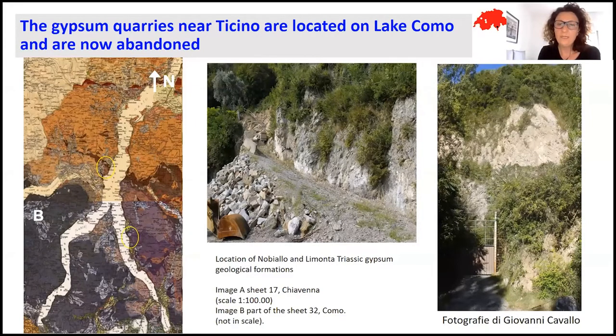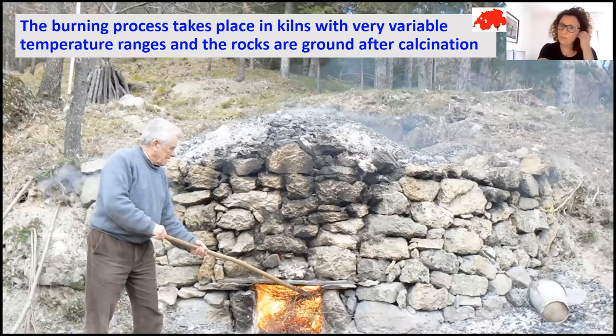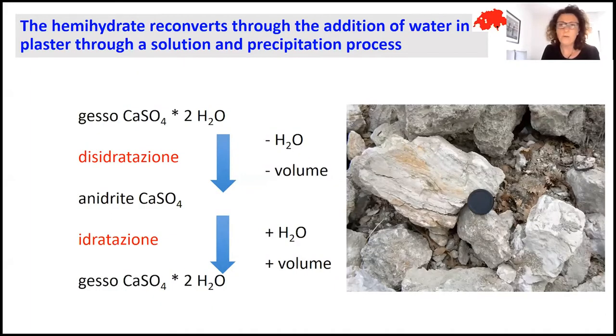The gypsum production process also took place in these traditional kilns, in which the temperatures were very variable. For the production of gypsum, the temperature is lower than the one needed for lime binder production, because normally the correct temperature is around 120, maximum 200 degrees. Gypsum is chemically a calcium sulfate with 2 molecules of water.